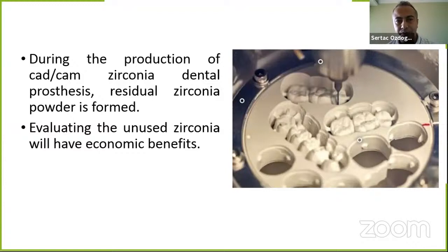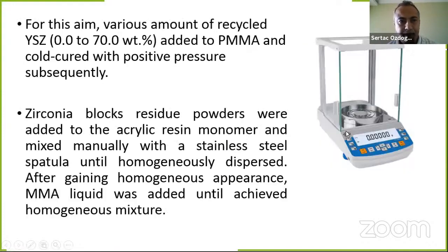During the production of CAD/CAM zirconia dental prosthesis, residual zirconia powder is formed, as seen in the picture. Evaluating the unused zirconia powder will have economic benefits. We can see the CAD/CAM process of the zirconia powder from zirconia discs. For this aim, various amounts of recycled YSZ were added to polymethyl methacrylate and cold cured with positive pressure subsequently.